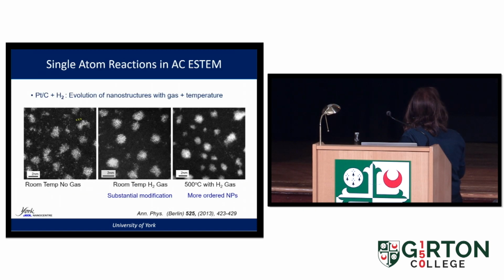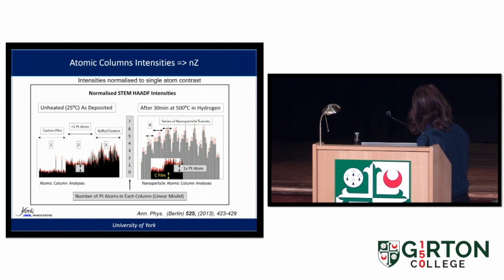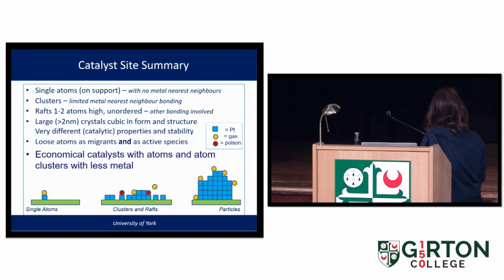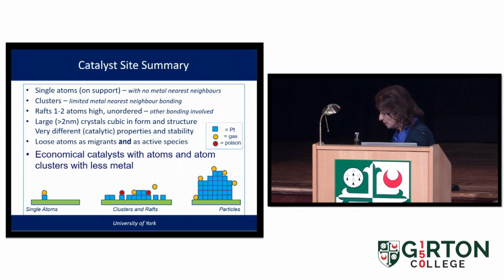Room temperature, no gas. With hydrogen gas, platinum starts to interact, as I showed earlier. And at 500, we get more ordered nanoparticles. They become much more faceted. And in fact, they've given up many of these surface atoms. So we can study all that at the single atom level. And we can quantify this, understand how many atoms there are in each column. I don't want to go into that. So basically, these atoms and clusters seem to be doing all the reaction, and the bulk is not doing anything. So it's leading to economical catalysts with just atoms and atom clusters with less metal. So you can imagine the consequences of that and the implications of that. That's what we are doing with Johnson Matthey at the moment.